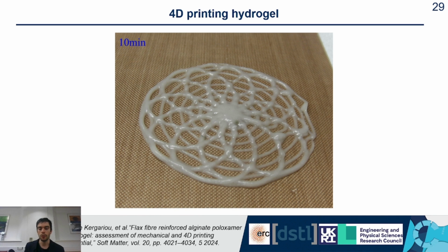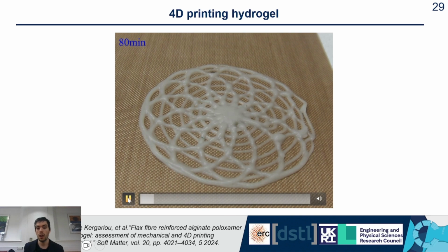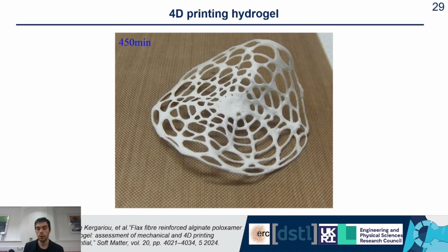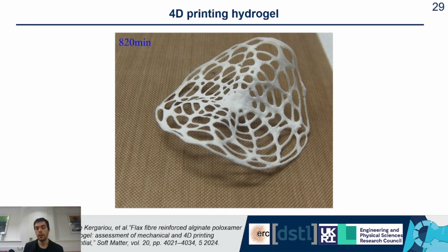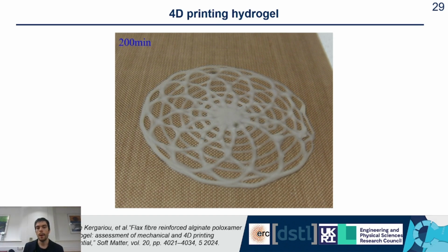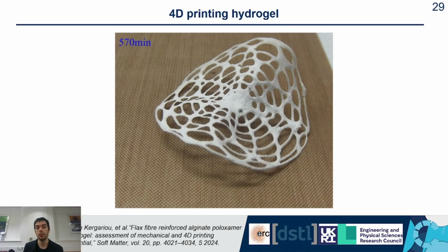That's what we did. I agree, it doesn't look a lot like Notre Dame, but still the inspiration is there. The first layer is concentric circles, basically. The second layer is more of a flower shape, and every single actuator is a contact point between the first and the second layer. So the actuation of the entire structure is controlled by the position of the contact points, the number of contact points, and the angle between the first and the second layer for each contact point. And so we can create complex actuation out of it. This was made with a much softer material, much easier to print, a flax fiber reinforced alginate hydrogel, and you can create that sort of complex actuation. This type of material has specific purposes for biomedical applications, for instance, to deliver drugs or to replace soft tissues.